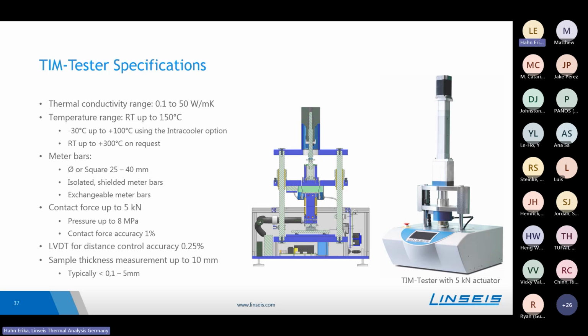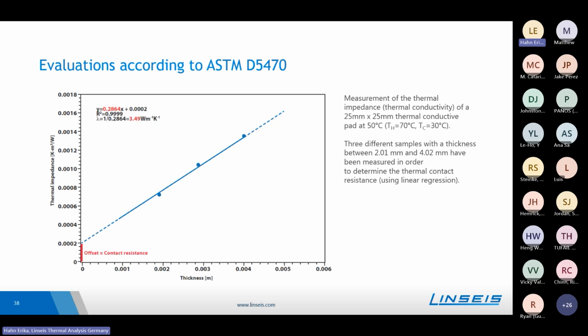This mentioned ASTM norm does not only describe how the instrument should be set up, but also determines how the measurement should be done as well as the evaluation. For determining the thermal conductivity of a material, it is necessary to test the thermal impedance of 3 different sample thicknesses. As the system will firstly measure the thermal impedance, which still has the influence of the contact resistance between the material and the meter bars, there should be a method on how to subtract this contact resistance.